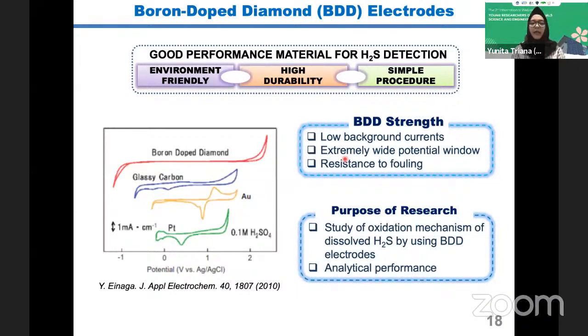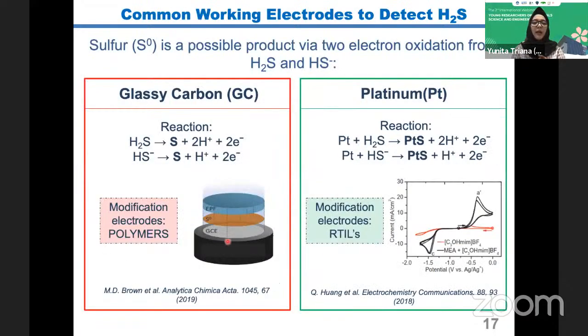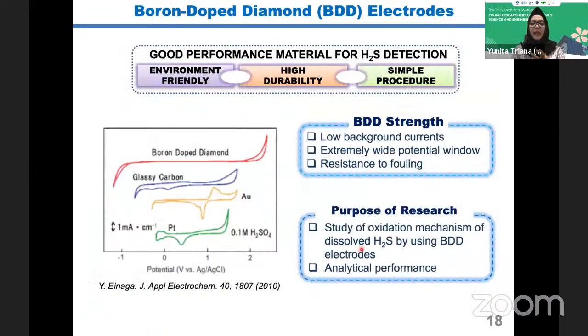And what is the BDD strength? BDD strength is low background current, an extremely wide potential window, like I show you in this red color, and also resistance to fouling. Why should it be resistant to fouling? Because on glassy carbon and Pt, sulfur can be formed when we react the H2S gas. And also, the purpose is to study the oxidation mechanism of dissolved H2S using BDD electrodes, and we will measure the analytical performance.